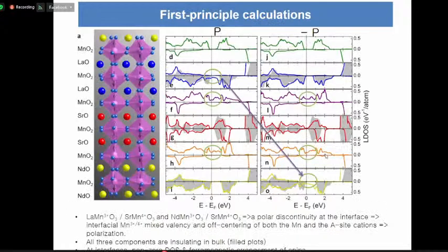Okay, my collaborator calculated these materials using first-principles calculations. Depending on the polarization, there is a spin-polarized, metallic behavior. There is a density of states. Then we change the direction of polarization. This is gapped, so this is not metallic, and there is no spin polarization. If we change the polarization direction, then instead of lanthanum oxide, the neodymium oxide shows a metallic and spin-polarized density of states like this. So these results show, depending on the polarization, the magnetism can also change. The layer is changed.